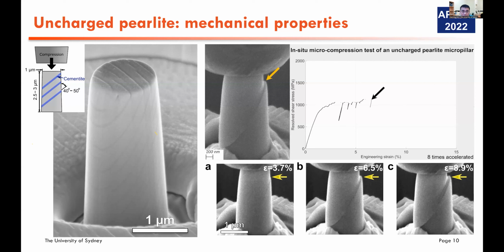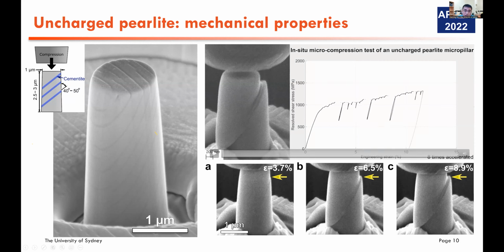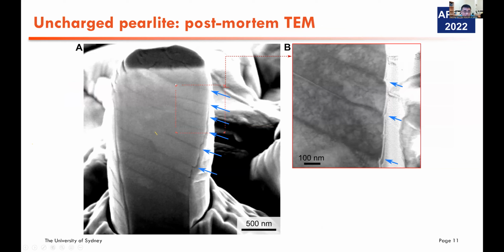You can see the slip propagates along the interface, and those intermittencies are called strain bursts, which reflect the collective dislocation behaviors in the slip plane. And after the compression test, we further slice this into a cross section and check the postmortem TEM images. As you can see here, the interface is really slipped, and the slip exactly happened at the interface.